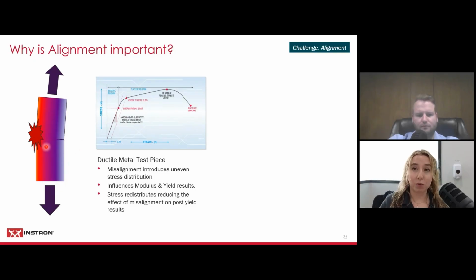And then after we've reached our yield, it's actually going to redistribute that load. So what that does is that if we're misaligned with a metal piece, our modulus is going to be affected and our yield is going to be affected. So our elastic region is affected. But once we've hit the plastic region, our ultimate tensile strength and our ultimate strain are actually not affected by that misalignment because we've been able to redistribute that stress within the specimen.